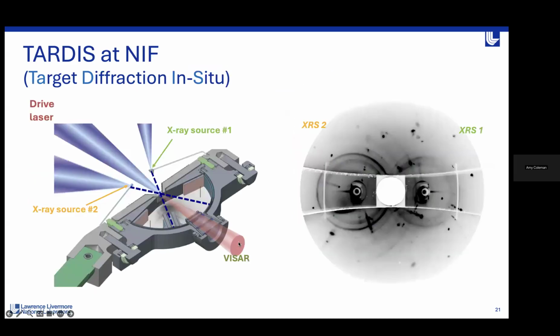When we're doing experiments on NIF, it's quite a similar setup. Instead of PXRDIP, we have something called TARDIS, which is our target diffraction in situ. And instead of a box, we have something that looks slightly more like a watermelon here. So we have image plates on the rind and on the top and the bottom. But still similar to the other setup, we have our target sitting on the front. We have our VISAR laser coming in the back to make a velocity measurement. But we also have two X-ray sources. So one bonus of doing these experiments at NIF is that rather than just taking one X-ray snapshot during our compression path, we can actually take two snapshots, which is great, double the data. That's a real bonus for us in terms of interpreting what's going on.